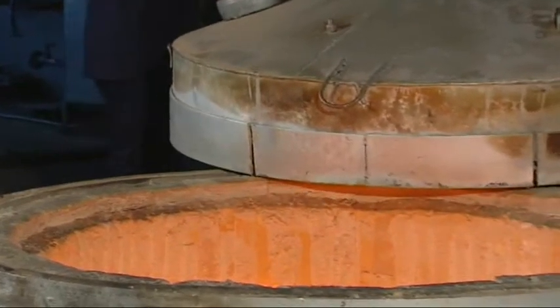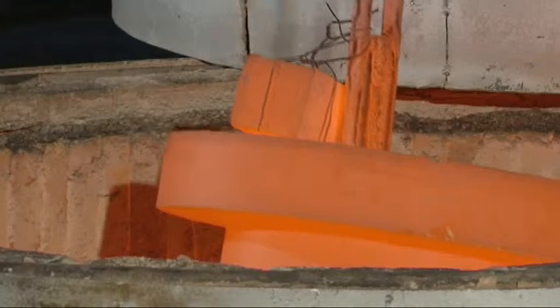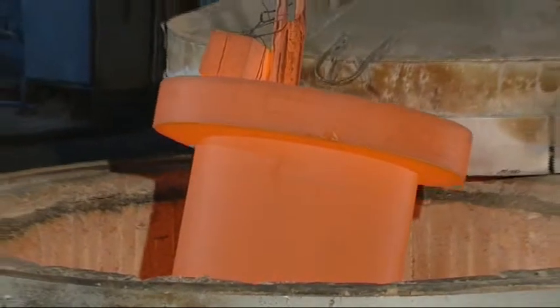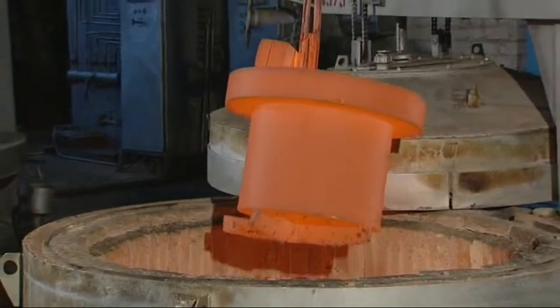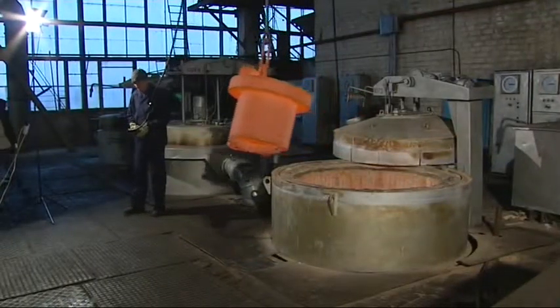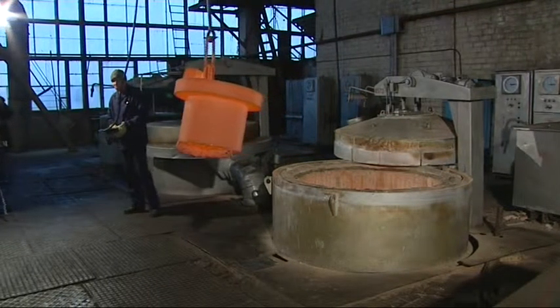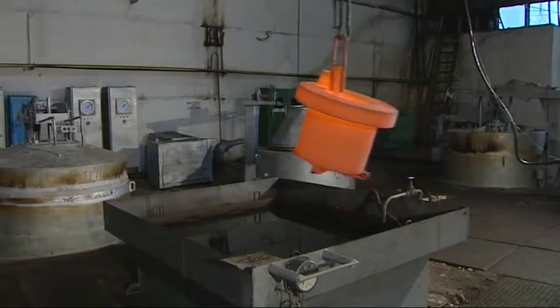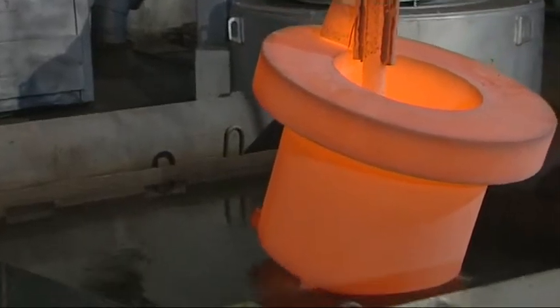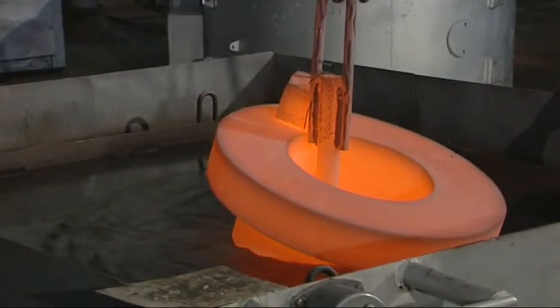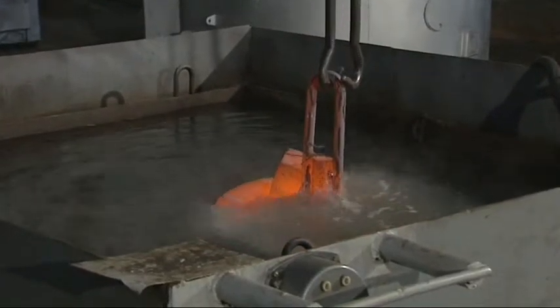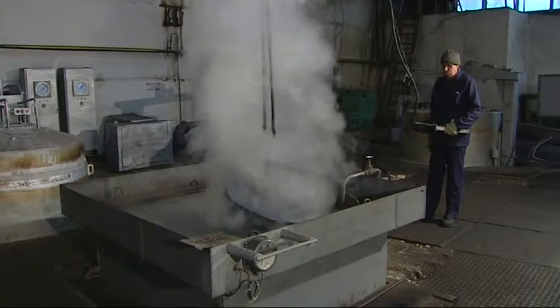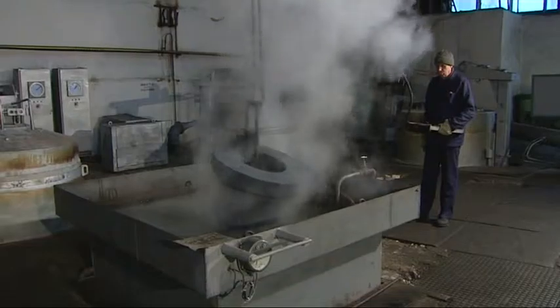To satisfy strength requirements, yield strength, percent elongation, impact strength and hardness values, each part is heat-treated, quenched and tempered. Parts are heat-treated in electric shaft furnaces and chamber furnaces. A qualification test coupon manufactured of material of the same heat as the part is placed into the furnace together with the part.